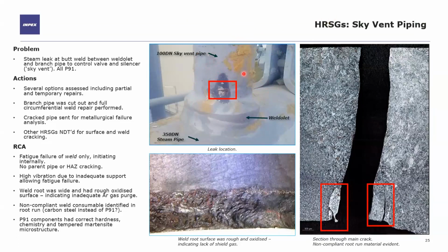However, two things jump out at us with that fatigue failure. One is that the root run of the weld was wide, rough, and heavily oxidized, which suggested inadequate shield gas. And metallurgical analysis showed that a non-compliant weld consumable had been used at the root run, closer in composition to carbon steel than to P91.